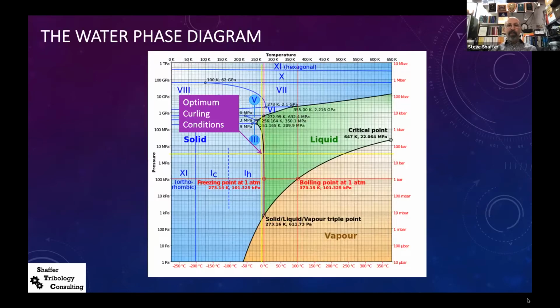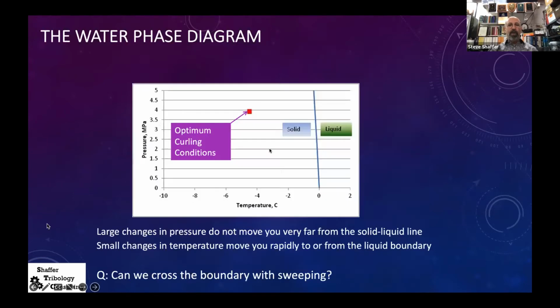So here's our optimum curling conditions shown right there. Notice the curve is quite vertical there. And if I blow this up, here's our curling conditions optimally, -4.5 C. We're at a pressure of about 3.8, let's call it 4 megapascals. And what we observe is that large changes in pressure, because the line is vertical here, really don't get us closer or further, not much, from the solid liquid interface line.